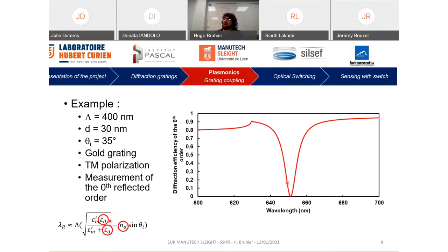We have here quantities related to the optical properties of the dielectric medium. So by changing the refractive index of the dielectric medium, we change these quantities, and so we change the position of resonance, and we can shift the resonance. These are the classical grating and classical setup for grating coupling, as Julie presents. But we will talk about a tiny difference in coupling, which is the optical switching effect.